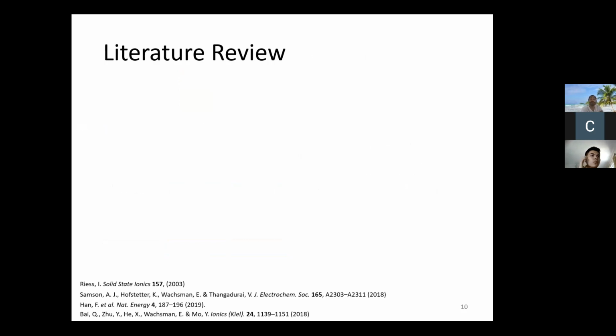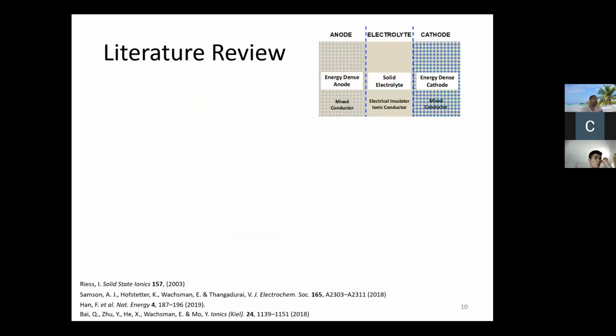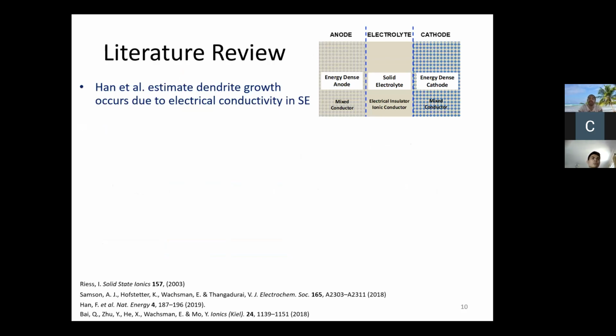And so currently, the state of the art, what we know in terms of investigating this, is that these solid electrolytes aren't perfect yet, or else I wouldn't have research to do, right? The one problem with solid electrolytes right now is that you still see some of this dendrite growth that you see in the liquid organic systems. The only difference is these don't catch fire, but they still get really, really hot, and basically you're losing your energy. Han et al. estimated that some of these dendrite growths really occur because there's still some electronic conductivity in the solid electrolyte material. And remember, we don't want electronic conductivity in the solid electrolyte in the middle of the material, right?